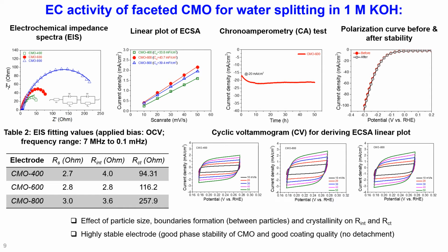The electrochemical impedance spectra, that is the EIS spectra of CMO 400, 600 and 800 electrodes, have been shown here. From this, the Rct values of the 400, 600 and 800 electrodes increase with the annealing temperature, which is due to the increase of crystalline nature. And then the R intermediate, that is the intermediate formation resistance of CMO 600, is much lower than the other two electrodes, which supports the higher activity of CMO 600.